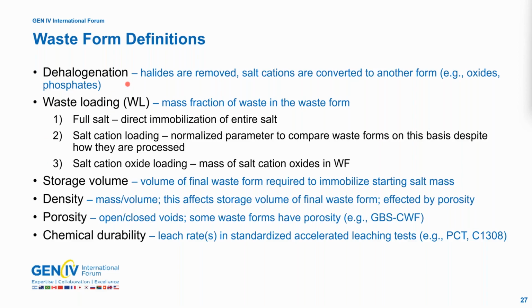So the dehalogenation process is a technique to remove halides from the salt. There's lots of reasons why you would do this. The main one I alluded to earlier is that immobilization of halides is quite challenging. So if you can remove them and deal with them separately, then the products that are remaining are converted to things like oxides or phosphates, and the waste form immobilization options are increased and are more straightforward. There's things like waste loading, which we define as the mass fraction of waste in the waste form. The term waste can be defined differently. So there's full salt, where if I've got a full salt that I have not partitioned, I can directly immobilize that. That's full salt waste loading.